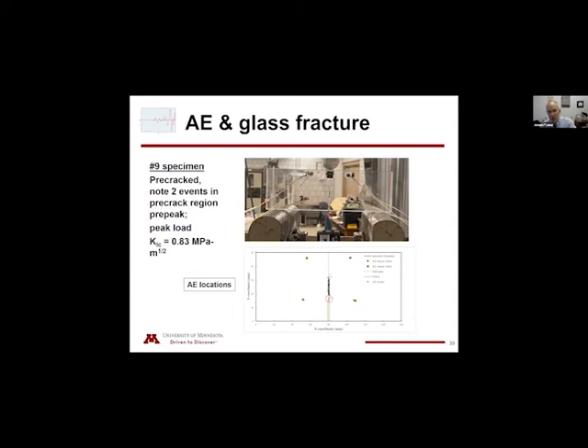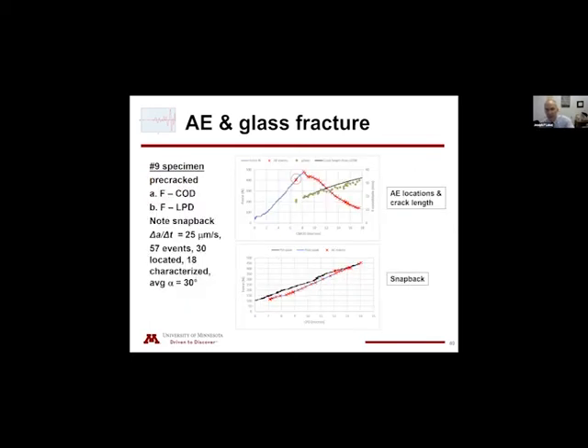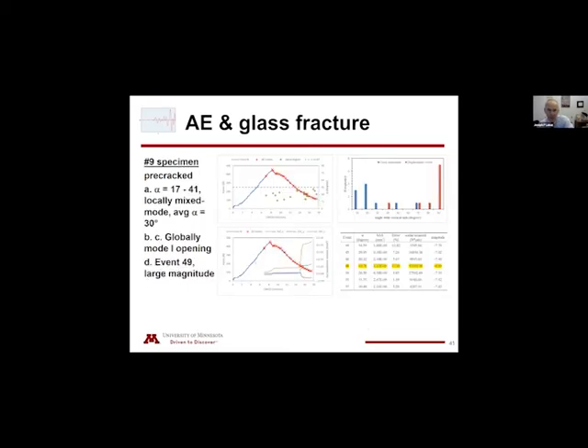These are the locations that track the crack. It's interesting to note that there are 2 events that take place within the pre-peak region. So possibly due to some interlocking that has taken place, we do get events along the pre-crack. We were successful in monitoring and controlling crack propagation, with similar crack speed to what we saw from the test with rock. Again, very strong snapback, and again, mixed mode character, locally opening.